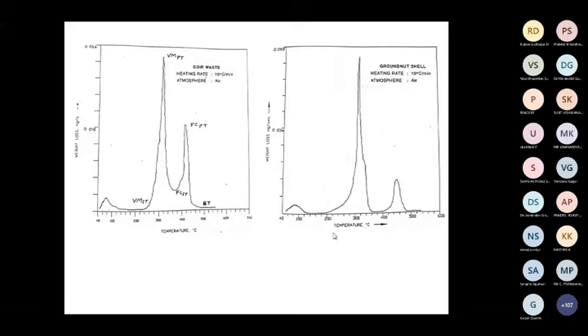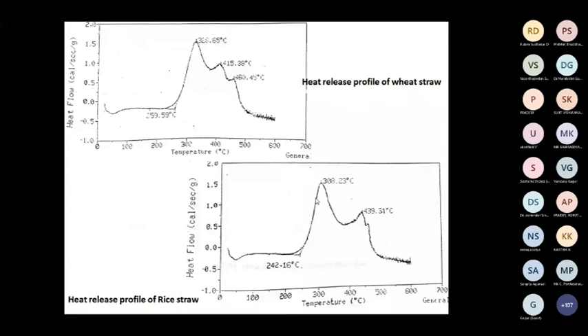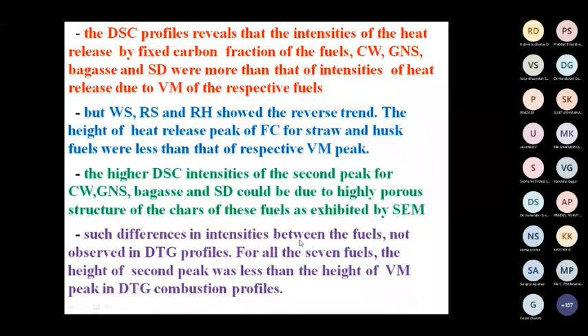Okay, so this is for other biomass fuels, DSC of wheat straw and rice straw. These two follow a trend similar to TG: rice straw, wheat straw, rice. See this observation. The DSC profiles reveal that the intensities of heat release by the fixed carbon fraction of coir waste, groundnut shell, bagasse and sawdust are more than the intensity of heat release due to VM. That is one of the peculiar observations compared to TG. But wheat straw and rice show the reverse trend: the heat release due to fixed carbon is lesser than that of the VM.